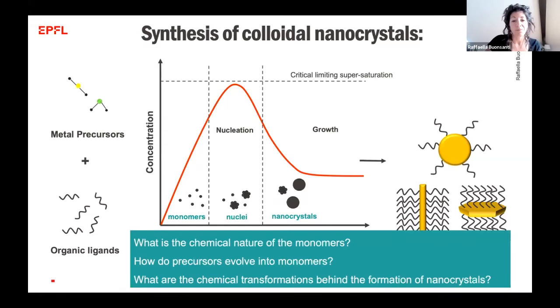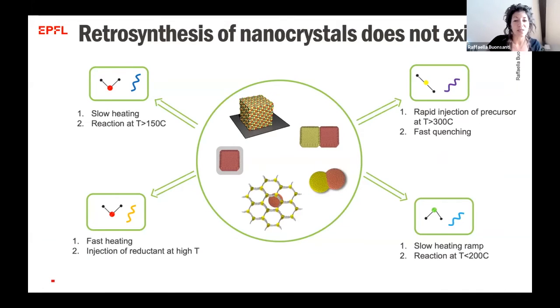But the truth is that we have very little idea of what these monomers are. We also have little idea of how the precursors evolve into the monomers, and generally what the chemical transformations behind the formation of nanocrystals are. And I do believe that it's because of this reason that retrosynthesis of nanocrystals still does not exist. So we cannot really define which precursors, which ligands and which conditions we have to use to eventually reach our target product. And this is the reason why Ray was mentioning earlier today that we might need a few years to learn how to synthesize new compounds.